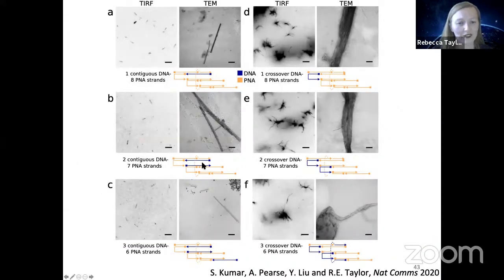And we also found that we were hoping to play with twist with these structures. And what we found was when we selectively introduced DNA instead of PNA, we thought maybe that over-twisted nature of DNA would allow us to twist our structures. But we saw the very opposite. We saw what looks like a massive stiffening. So this is definitely the uncooked spaghetti model. Massive stiffening of our structures. And it happens with 1, 2, and 3 to the same extent. So we're really excited about this phenomenon.